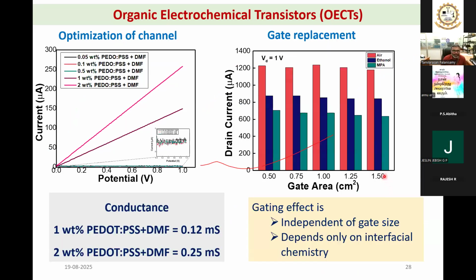And now we have optimized the electrolyte or the dielectric gel polymer. On the other hand, we also have to optimize the channel and gate. On the channel, as I told you in the previous study, we used DMF as an additive, and here also we have used DMF. There we optimized with different solvents, but here we directly used DMF with the previous knowledge. And you can see here when I change the PEDOT:PSS weight percentage, we got gradually increasing conductivity. For instance, at 2 weight percent, we got the highest conductivity.